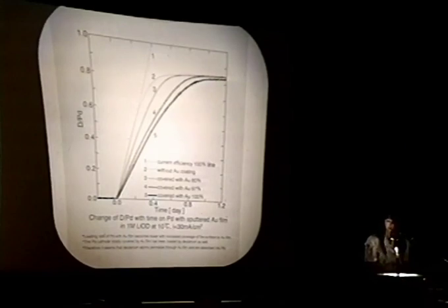The palladium cathode totally covered by gold film has loaded by deuterium as well. Therefore, it seems that deuterium atoms permeate through gold film and are absorbed into palladium.